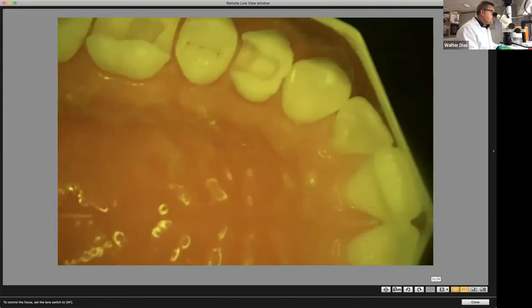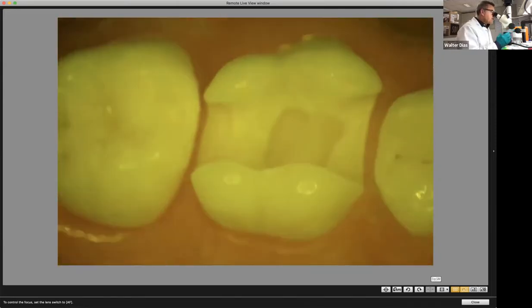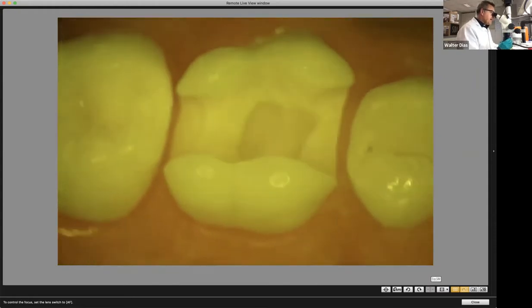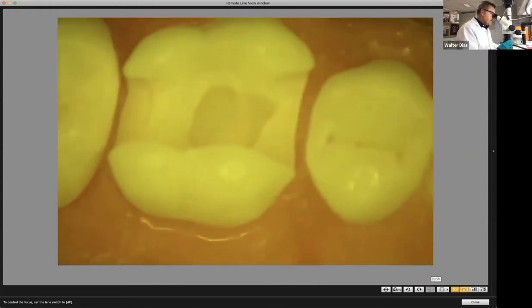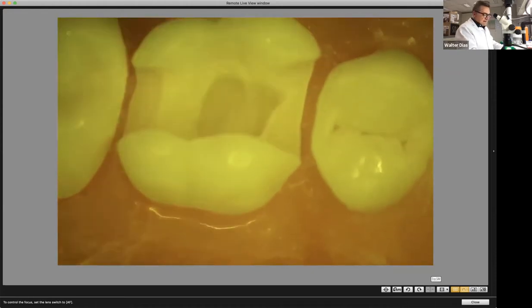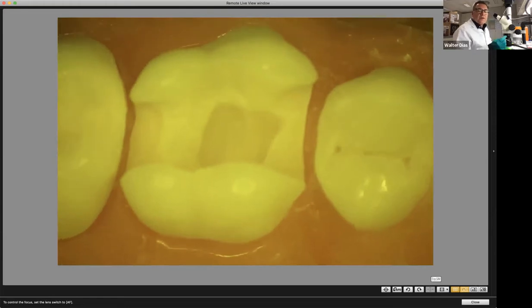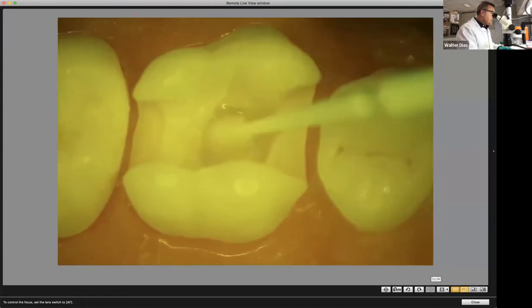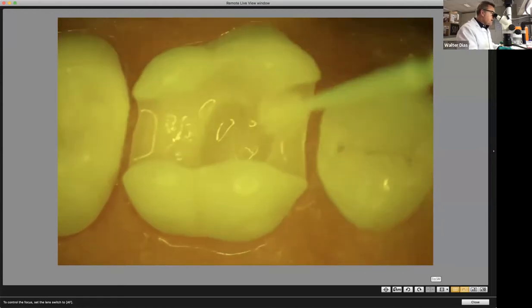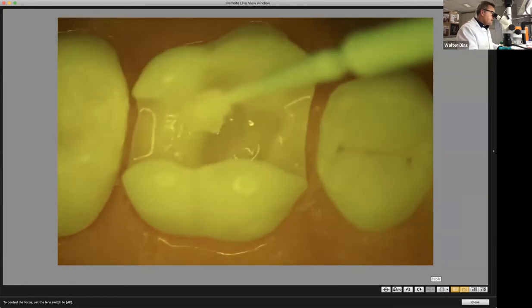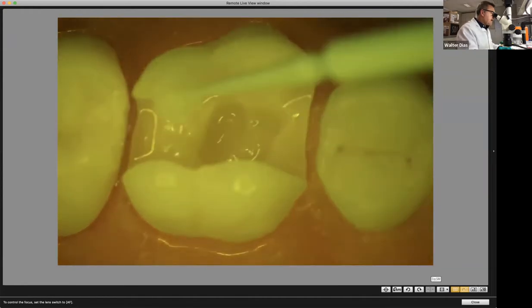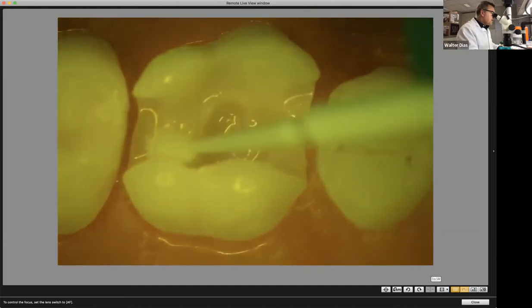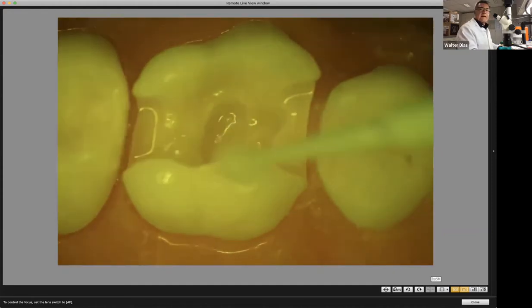Yeah. Now, the same thing here. We're going to etch the enamel. We're going to etch the sclerotic dentin and the hypermineralized dentin. And then we're going to rinse and dry without over drying. Don't etch the normal dentin, okay? And then we're gonna apply it normally as we did before. I always like to apply it massaging the non-etched dentin, and then I extend to the enamel, okay? So I'm gonna prepare this afterwards.